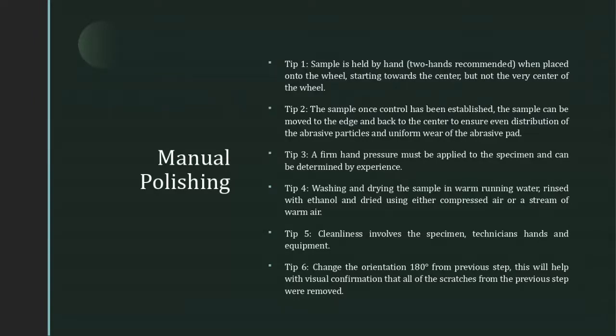You're going to place it not in the very center of the pad. Since it's spinning, if you place it a little awkwardly, it'll take your sample out. So what you do is just go just to the right, just below center. I'll discuss sample placement on the pads when we get into the lab, and we'll have a video showing all that. You want to place it just offset from the center, because that's the part of the wheel that does not have the angular velocity you'd have on the outer edge. So the chance of the sample flying out of your hand is far less by being placed closer to the center.